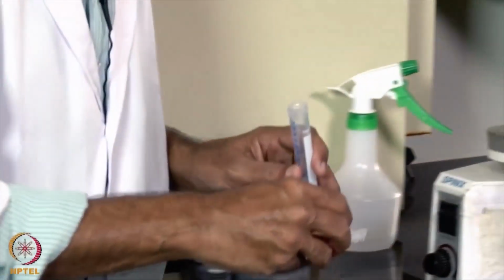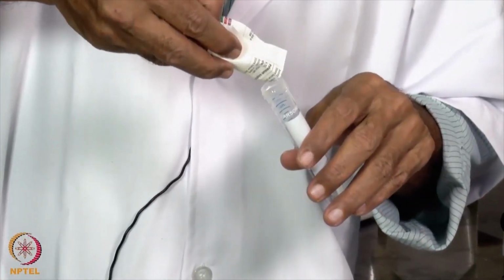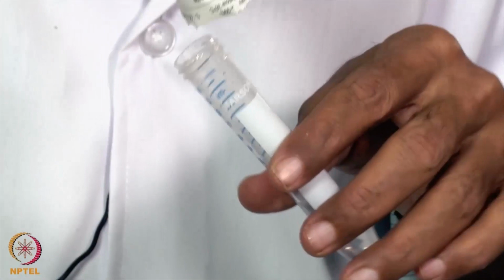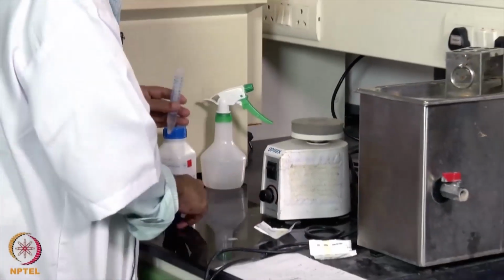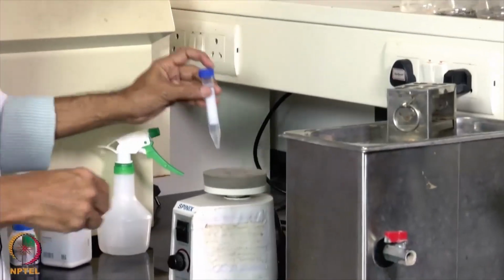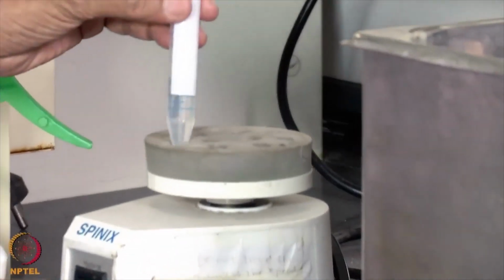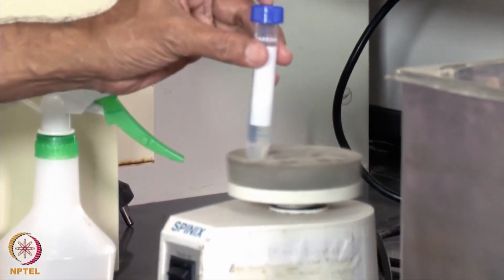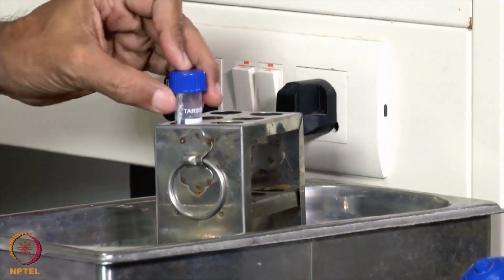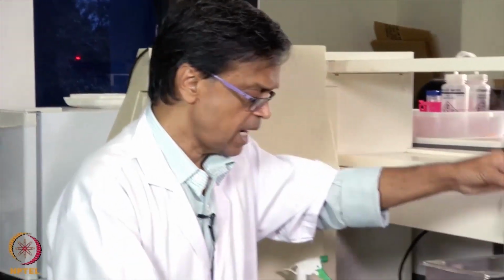Once that is done, we add cyclic beta glucan, which is 18.75 milligrams, to this. Again we heat it up to 70 degrees centigrade, mixing it from time to time. We add 0.75 milliliters of glutaraldehyde. Glutaraldehyde is a cross-linking agent, so it will cross-link the carrageenan and the beta glucan. That is, this is 1%, so we add it to this.